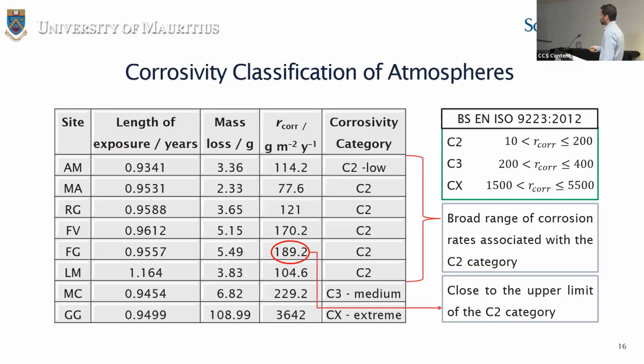However, there is a broad range of corrosion rates associated with these sites within the C2 category, with the highest at FG, which is 189.2 grams per meter square per year, and this is close to the upper limit of that category. Then you have the mid-island atmosphere MC having a higher corrosivity category, and GG is of the highest corrosivity category.